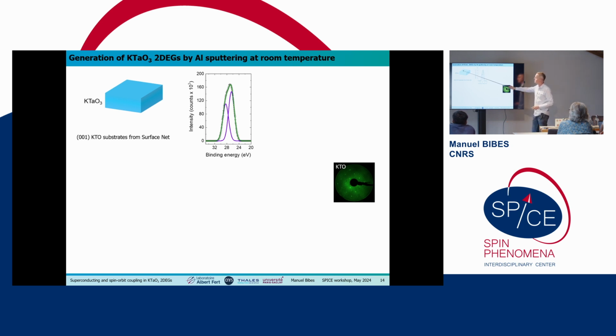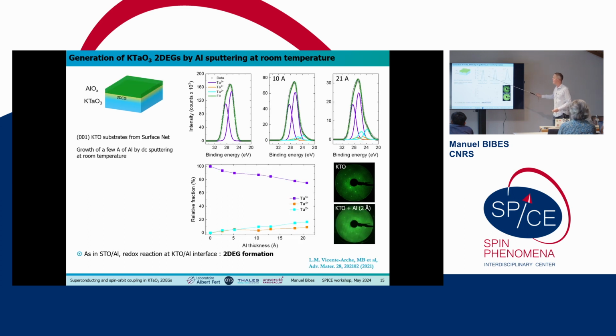So we start with a single crystal of potassium tantalate. Now this is 001 oriented potassium tantalate. This is important to remember, the orientation. It's 001 for the moment. And then we are going to deposit a little bit of aluminum, by sputtering in our case. And to monitor what is going on when we do that, we do XPS and we look at the tantalum levels. This is before depositing any aluminum, and the tantalum spectra correspond to pure 5+ stoichiometric tantalum. And then when we grow aluminum, here 10 angstrom, 21 angstrom, we see these shoulders that correspond to the reduction of tantalum, meaning that we are putting electrons in the system. So we're actually reducing the tantalum by putting aluminum.